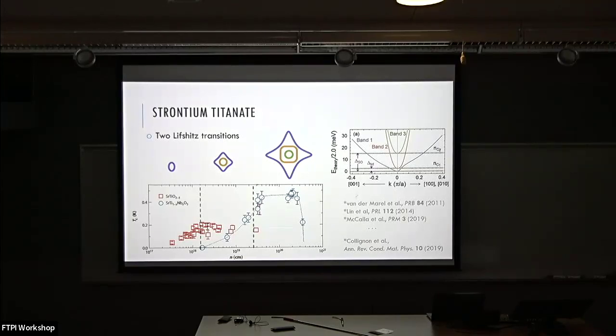Okay, and then yeah, with doping, you basically move up in this band structure, and it is again mostly assumed that these bands are rigid. They don't change much. Of course, this also depends on the type of dopant. So the band structure, especially in the low region, is a bit different for oxygen than for niobium doping. Now, this is something I will mostly ignore for now, because one reason is that we will focus on dopings that are here somewhere. Here, the difference is not that big, but this is also definitely something to do.